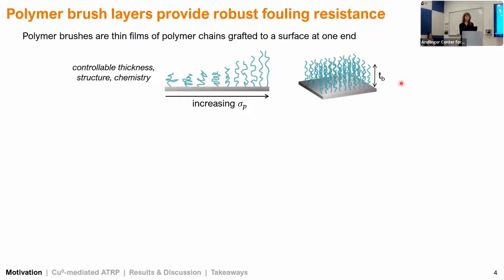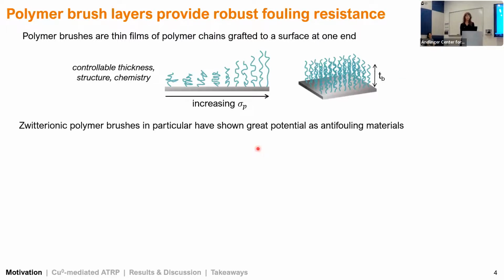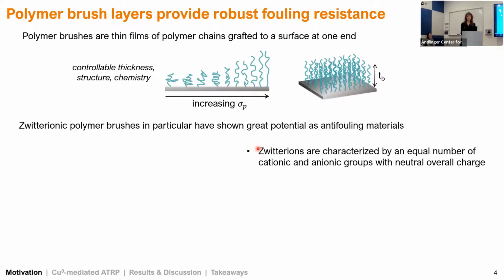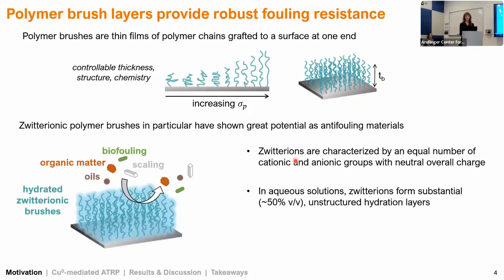So one surface chemistry in particular, zwitterionic polymer brushes, have shown great potential for anti-fouling layers. Zwitterions are characterized by an equal number of cationic and anionic groups, so they have a neutral overall charge. And when we put them in water, they form these substantial, strongly bound, and also unstructured hydration layers. And this gives us very strong hindrance to the attachment of various types of fouling. And the polymer brushes themselves also provide steric hindrance because they resist compression. So this is all great. They work really well. What's the problem?